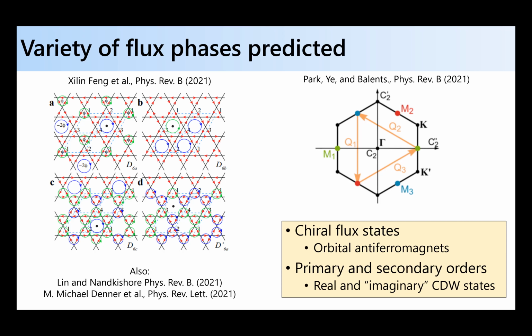Okay. So just to highlight a little bit of terminology. On the kagome lattice, there's a variety of what some people call flux phases, which are these orbital antiferromagnetic phases where you have loop currents which are modulated across the unit cell. There are a number of different patterns that are predicted if you can tune it towards these Van Hove points. The way to think about this is that the charge density wave state can have real or imaginary components, and the imaginary component is really what's driving this orbital antiferromagnetism, okay? And of course, of the real and imaginary components, one can be primary or secondary to the other. So there's a rather complex space that can manifest, which makes these systems interesting. A lot of different states can potentially emerge.